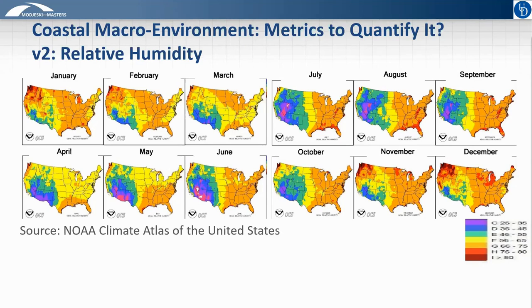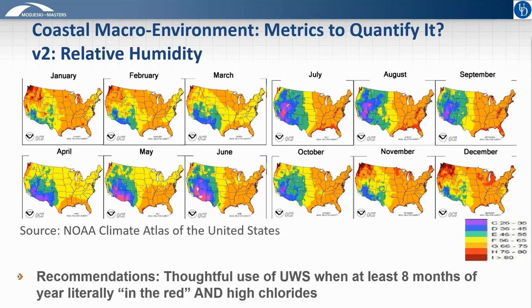So again, based on looking at field performance data, we see a correlation when that level of humidity occurs for at least 8 months of the year. In other words, if 8 or more months of the year are in the red, meaning an average relative humidity exceeding 75% for most of the year, we possibly have an excessive level of humidity. From a rough skim of these figures, you can see this generally occurs along a relatively small but important portion along the Gulf coastline. And at these lower humidity levels, compared to the time of wetness threshold, significant chlorides are also necessary to be simultaneously present in order to cause accelerated corrosion at levels that may be of concern.